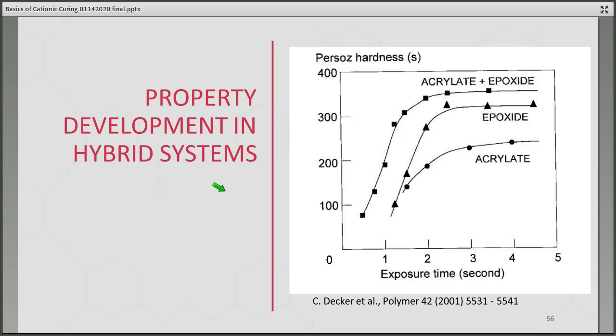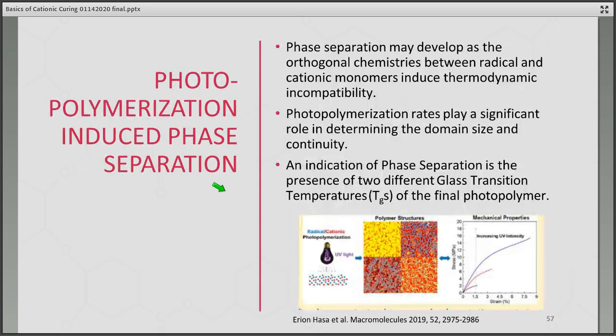However, the best hardness obtained was actually the hybrid system. Instead of coming out with what seems to happen most often, where you get something that's a compromise, it actually combined, and you got a much harder cured photopolymer than you did with individual components. So this kind of, I thought, very nicely illustrates how hybrid systems can work to your advantage.